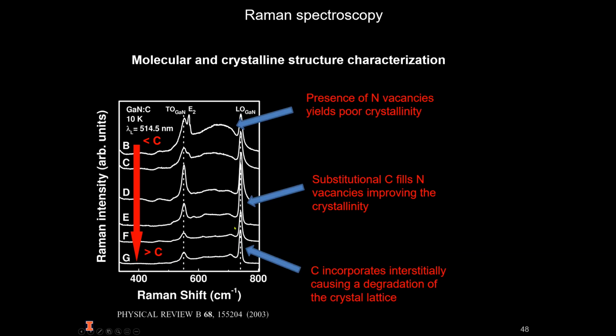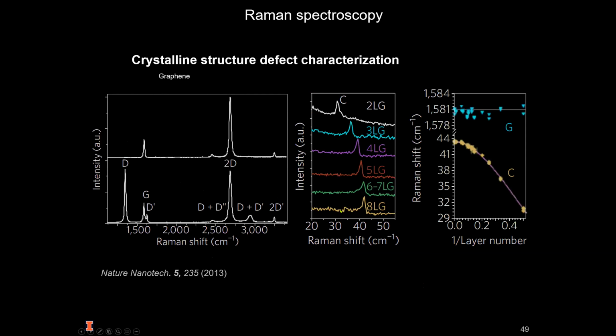Raman is also frequently used to study lattice defects in 2D materials, where the allowed vibration modes will drastically change with the presence of defects. This is illustrated here on this graphic that compares the pristine, monolayer graphene Raman signal with a defective graphene layer.